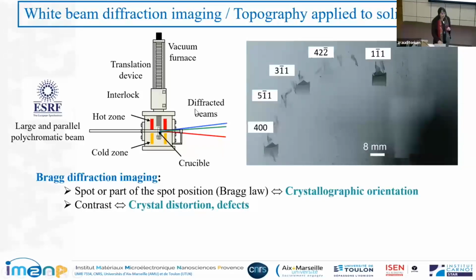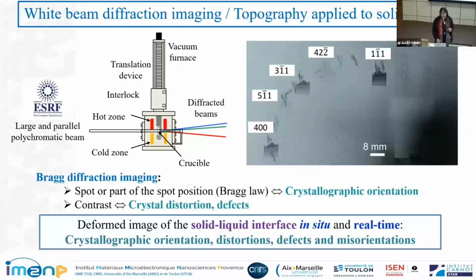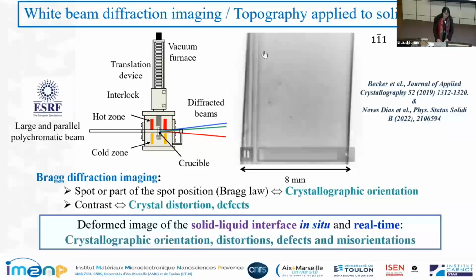So what do we do at the same time as we record the direct beam to have the radiography? We also record the diffracted beams here, and we have a look at what we have inside the diffraction spots, which is a topograph. And then we get key complementary information about the crystallographic orientation, the distortions, defects, and misorientations in our samples. And recently, together with the ID19 team, we improved the time resolution during this kind of experiments. Initially, we recorded these topographs on films. And now we can synchronize several cameras that focus on these topographs with sufficient spatial resolution. And this is what we get here.